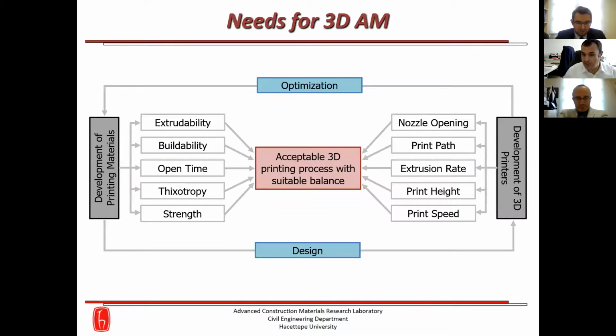And for the design parameters suitable for 3D additive manufacturing, there are some additional properties that we need to consider during the design of the special material. For example, printing material has to possess some specific properties related to 3D additive manufacturing in the fresh and hardened state, as shown in this figure: extrudability, buildability, open time, thixotropy, strength. And the printer should be designed by considering the target printing material properties. In this regard, printing process parameters, for example, nozzle opening, printing path, extrusion rate, print height, or print speed should be adjusted or determined to suit the characteristics of the material.